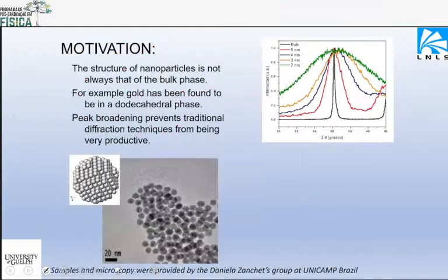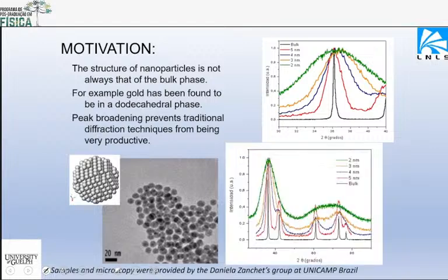Now, when we looked at nanoparticles, these are Daniela Zanchet's samples of gold nanoparticles. And on the right, you see what happens as the nanoparticles get smaller: that first Bragg peak just gets broader and broader and broader. It's terrible. And the whole diffraction pattern looks ruined. So the 2 nanometer particles are this worse curve like this. You can't measure Bragg peaks. The peaks are all overlapped.